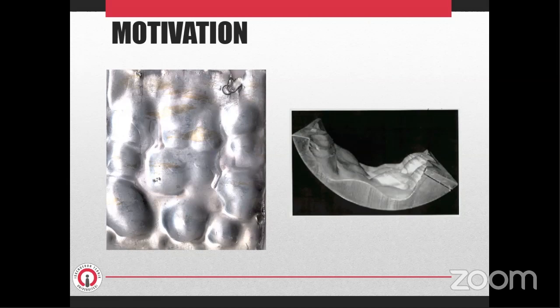On the other hand, if the solidification is not interrupted, the periodic variations at the freezing front tend to die out toward the end of the process, since the conditions at the liquid-solid interface become less dependent upon the conditions at the mold-shell interface due to the increasing solidified shell thickness.